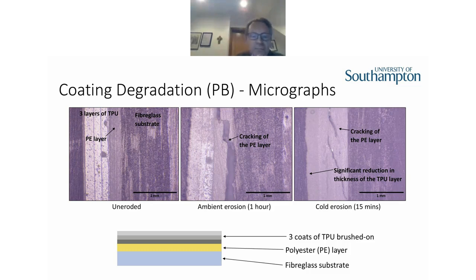We looked at sectioning to see just what was happening subsurface. So again, this is the 3 layered brushed polyurethane system on top of a polyester, and then you've got the fiberglass on the right. So the top surface is on the left here, and then you end up into the fiberglass to the right. You've got the uneroded system on the left hand side. In the middle you've got the ambient case that's been eroded for an hour, and on the right hand side you've got cold erosion after about 15 minutes.